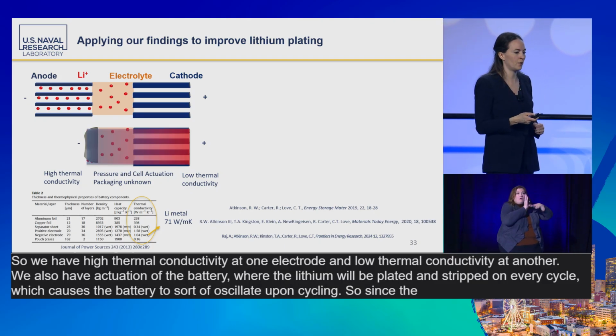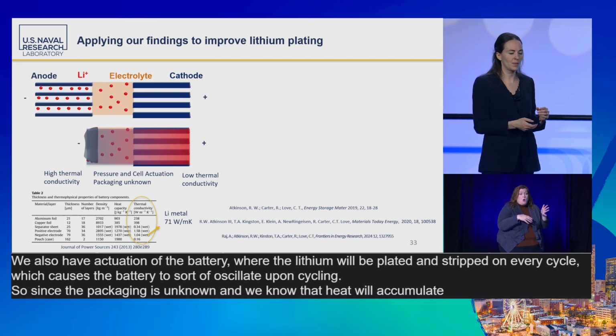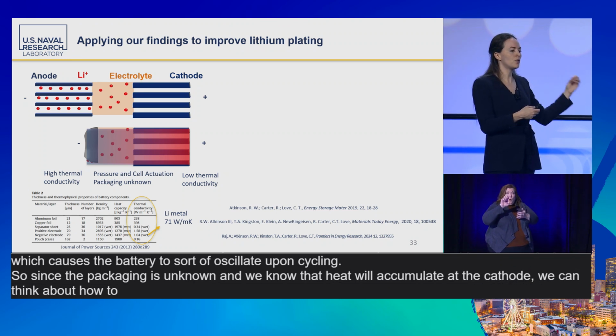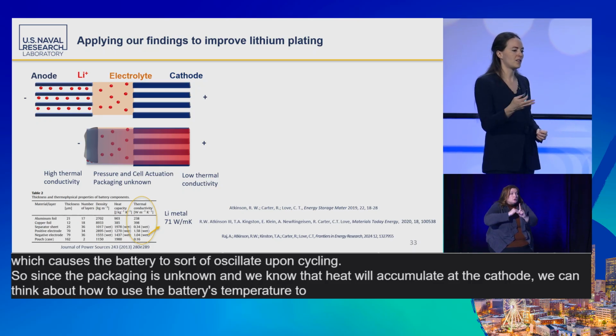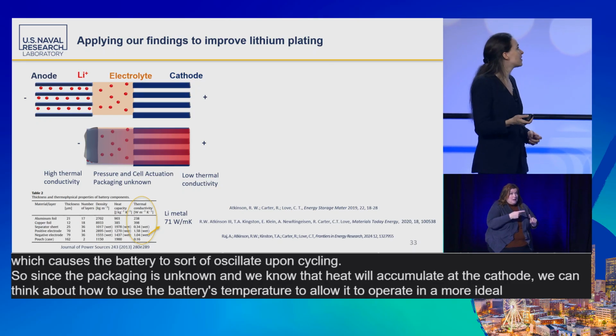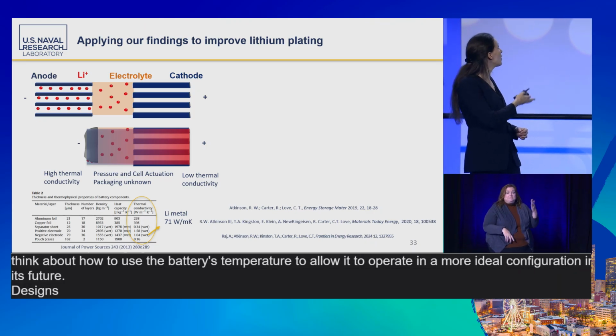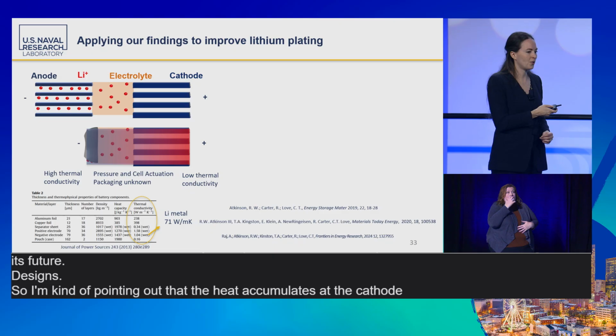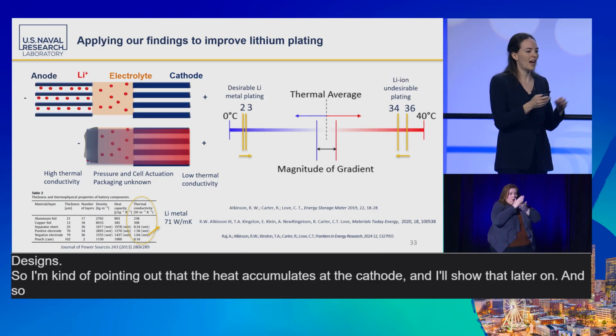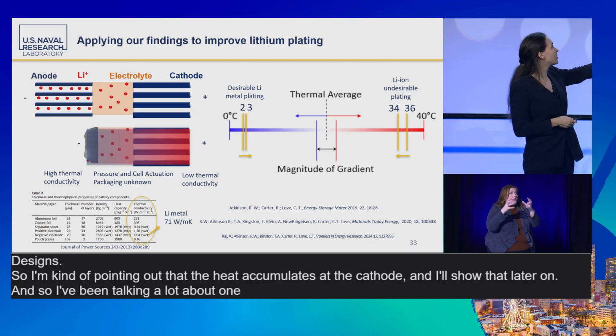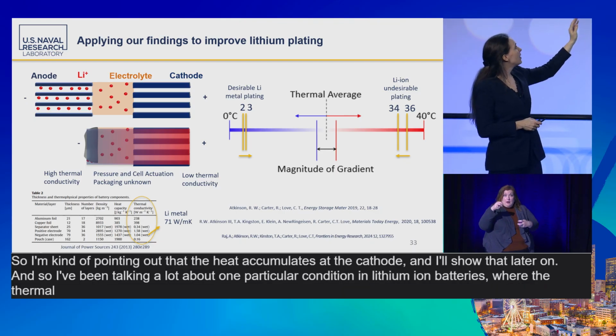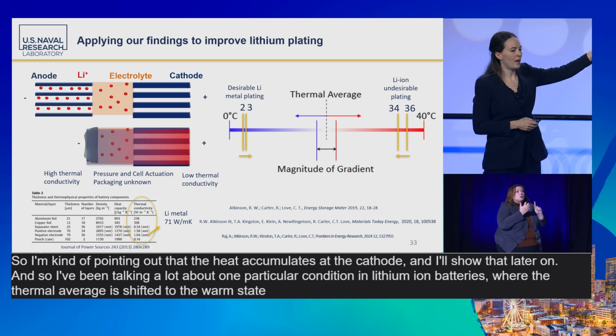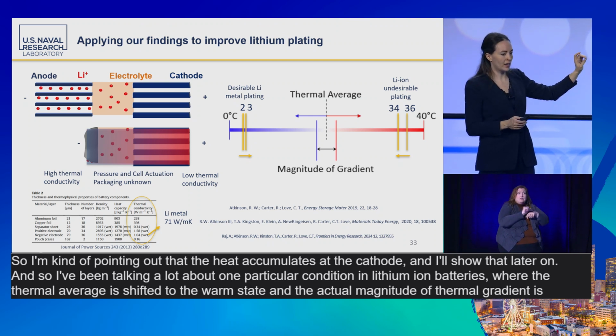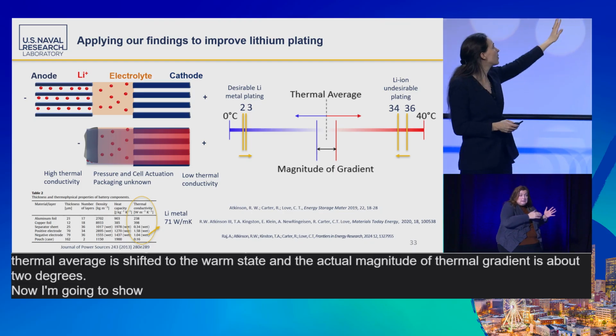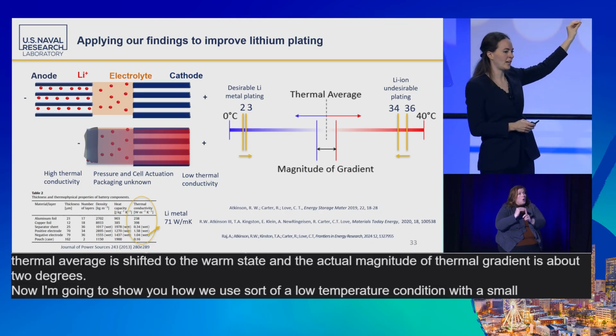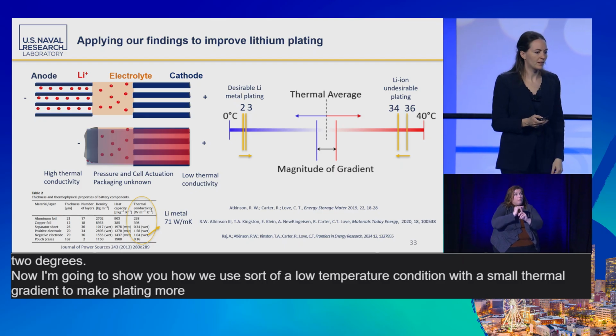So since the packaging is unknown, and we know that heat will accumulate at the cathode, we can think about how to use the battery's temperature to allow it to operate in a more ideal configuration in its future designs. I'm pointing out that the heat accumulates at the cathode, and I'll show that later on. I've been talking a lot about one particular condition in lithium-ion batteries where the thermal average is shifted to the warm state, and the actual magnitude of thermal gradient is about 2 degrees. Now I'm going to show you how we use a low temperature condition with a small thermal gradient to make plating more desirable.